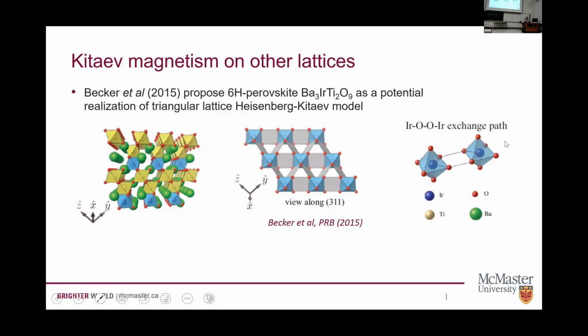Okay. So I started out trying to convince you that what was important for these Kitaev interactions was having a really special bond geometry with these heavy atoms that gave us strong spin orbit coupling. But more recently, about 8 years ago, there was a proposal that you could also try and get to a Kitaev interaction using sort of a different design principle. So instead of doing directly edge sharing octahedra, you could have octahedra that had parallel edges, but some spacing between them. And so the model material that was proposed here was what we call a 6H perovskite, this barium iridium titanium oxide 3129. And it was proposed that this could be maybe a triangular lattice Heisenberg-Kitaev material.